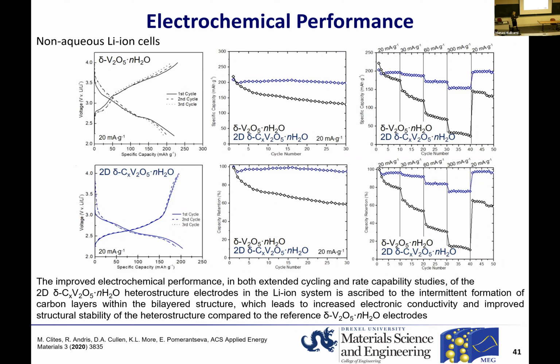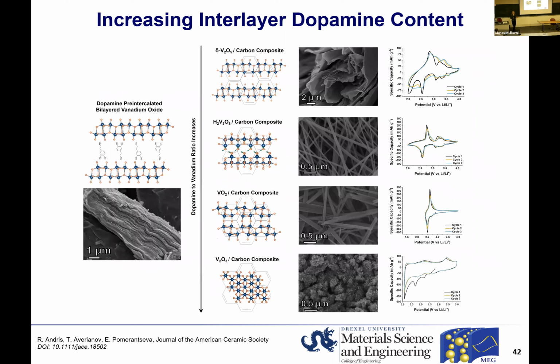But like I mentioned, with imaging, we only saw small areas where we could observe this carbon layer. So our next step was trying to increase the dopamine content during synthesis in order to increase the amount of the carbon precursor, to have continuous layers of carbon in the final product. But what we've learned is that as we increase the concentration of dopamine in the synthesis, apparently it also starts playing a role as a reducing agent. And in addition to serving as a carbon precursor, it reduces vanadium oxide.